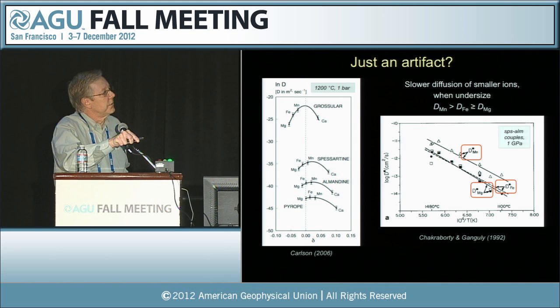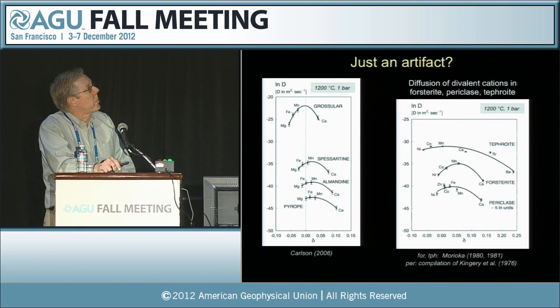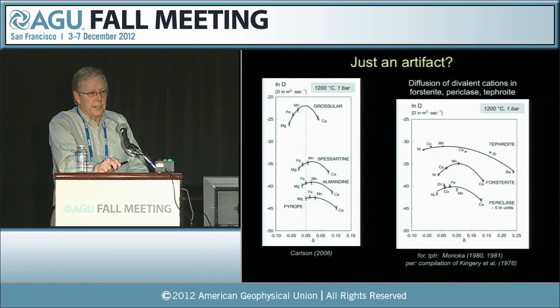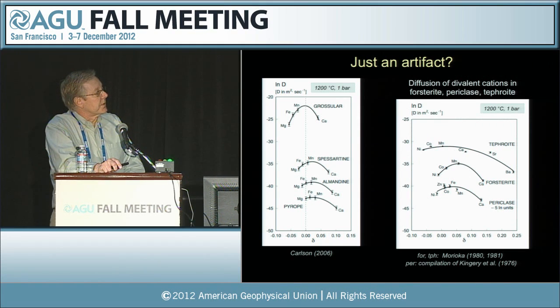So here we have manganese diffusing half an order of magnitude more rapidly than these smaller atoms in spessartine-almandine couples. And when I went looking in the literature, I didn't have to go too far to find examples of similar behavior. Here again, plotted at exactly the same scale.